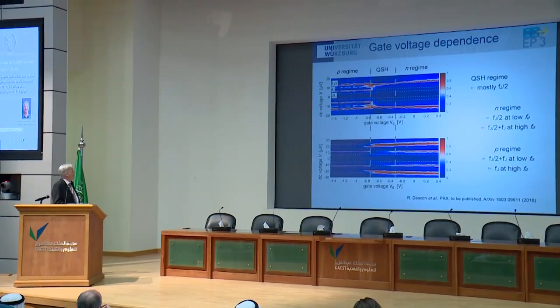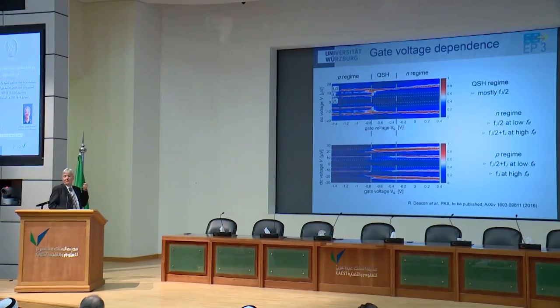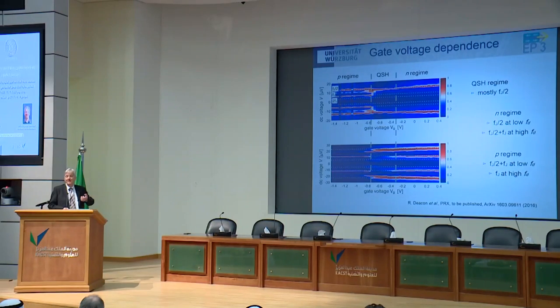We also see emission from the zero mode when the Fermi level is in the bands. And we think we can understand that this is occurring because these edge modes have different K vector than the bulk modes. So these edge modes do not mix very strongly, and they're actually predominantly strong in carrying the superconductivity.